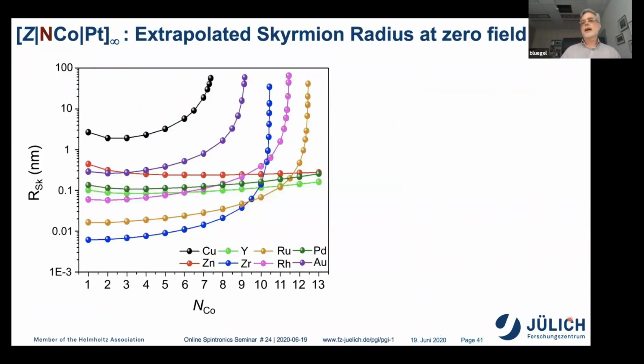Then I look here at the extrapolated values. So now I'm looking at the Skyrmion radius as function of the cobalt thickness according to this expression which I have shown before. And you see, first of all, that the Skyrmion radius varies even already for the monolayer, depending on the material, by 3 orders of magnitude. But what you observe is if you increase now this cobalt layer, the shape anisotropy becomes larger and larger. And you come to this critical point and you see how the Skyrmion radius changes. That means if you now fabricate your solid and you have an average slightly more cobalt or slightly less cobalt, your Skyrmion radius varies a lot from the point of undetectable by your characterization tool to too large.